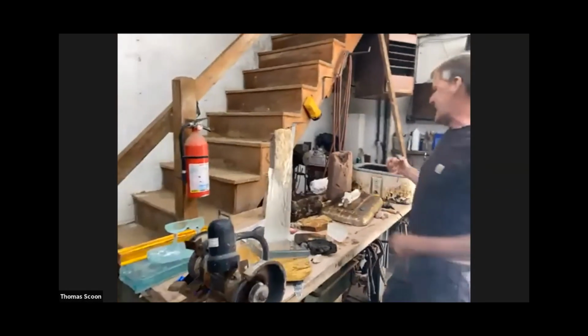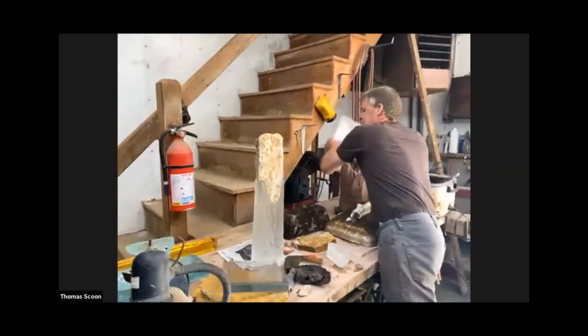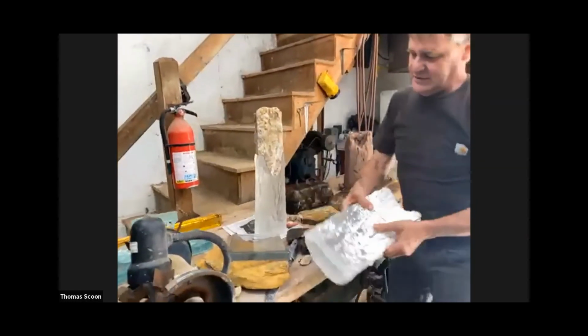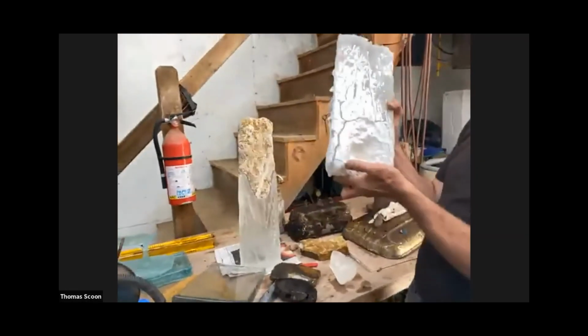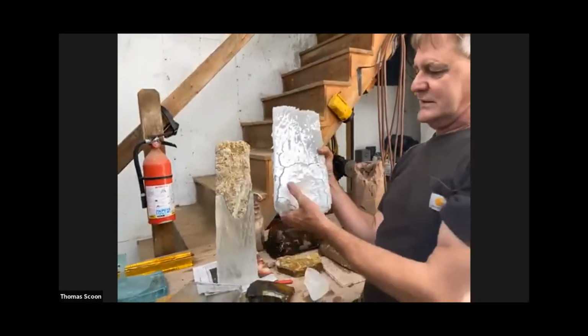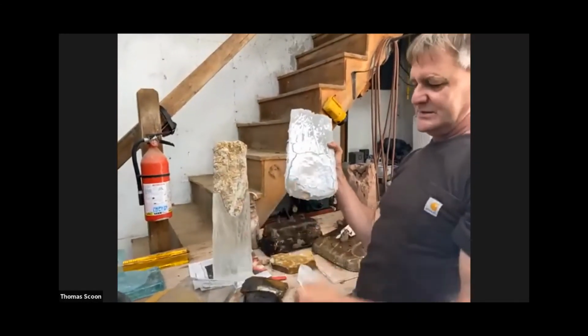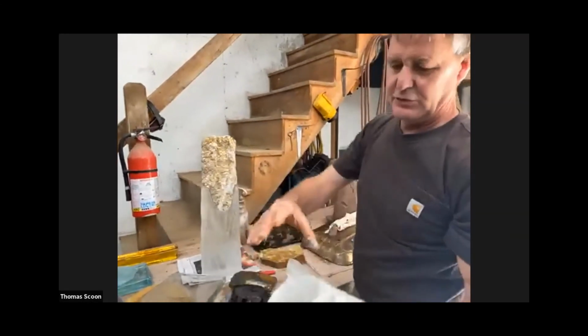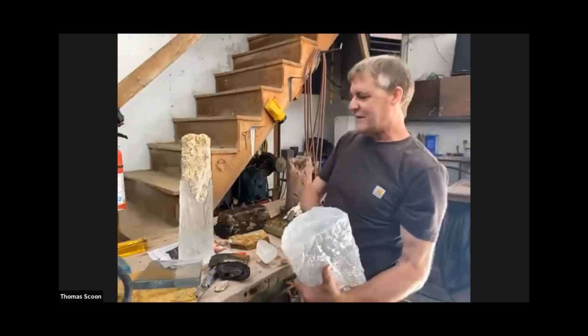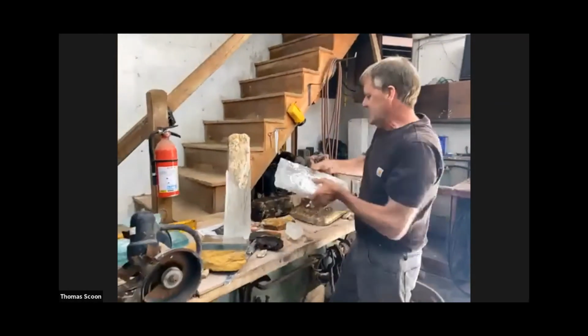Here's a piece that was actually just something recent. The mold failed. What happened was it's in the kiln like this, the mold cracked, and glass started coming out the sides and out of the bottom of the kiln, and it lost 3 or 4 inches off the base, so it's too short.